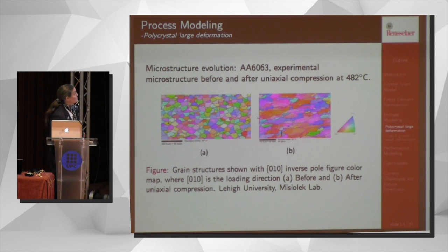Okay. Here's another example. This one we did have experimental data, and this was an aluminum alloy 6063. And these are experimentally observed microstructures. So this is the homogenized microstructure beforehand. It has fairly random orientations. We see lots of different colors there. And the grains are fairly equiaxed.